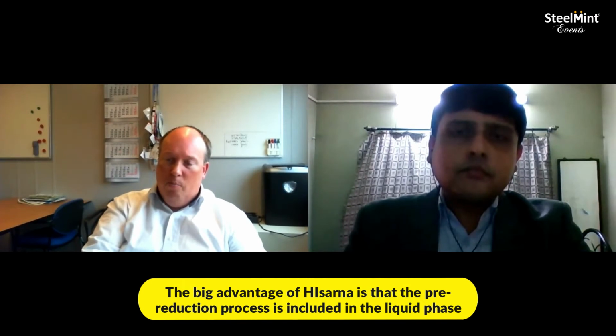Yeah. So if I look at smelting reduction processes, I think HIsarna has a big benefit over, for example, Finex or HiSmelt, in that the pre-reduction stage is included in the liquid stage of the reactor, which makes it extremely efficient. Basically, what normal processes do, the blast furnace included, is that you do a lot of the pre-reduction in the solid phase, which is slow and inefficient, and then melt everything and then do the final reduction. With DRI, it's pretty much all in the solid phase. In HIsarna, basically you melt everything first and then you do the chemistry, and that makes the chemistry really fast.